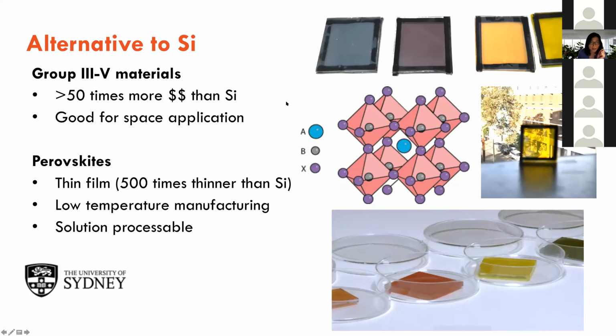Another alternative is perovskites, which a lot of you would have heard of already. What's so good about this material is it has very good electronic properties. It has very good optical absorption, and we can make it thin. We can make it 500 times thinner than silicon, and we can process it at low temperature. In silicon, the purification process and all the doping process take 1,000 degrees, whereas in this case, it's only 100 to 200 degrees. And it can be processed by solutions.